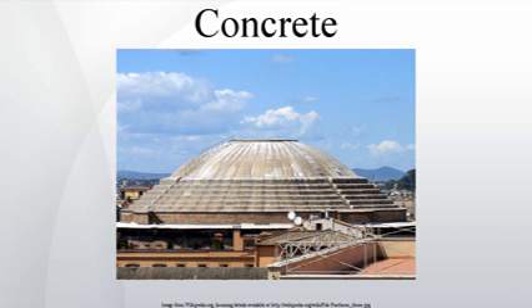Microbial concrete. Bacteria such as Bacillus pasteurii, Bacillus pseudofirmus, Bacillus cohnii, Sporosarcina pasteurii, and Arthrobacter crystallopoietes increase the compression strength of concrete through their biomass. Not all bacteria increase the strength of concrete significantly with their biomass. Bacillus sp. CT5 can reduce corrosion of reinforcement in reinforced concrete by up to 4 times. Sporosarcina pasteurii reduces water and chloride permeability. B. pasteurii increases resistance to acid. Bacillus pasteurii and B. sphaericus can induce calcium carbonate precipitation in the surface of cracks, adding compression strength.